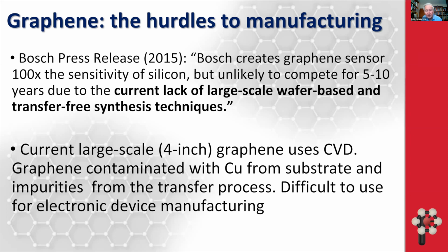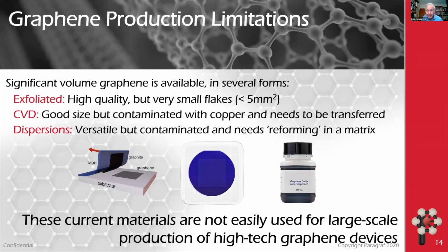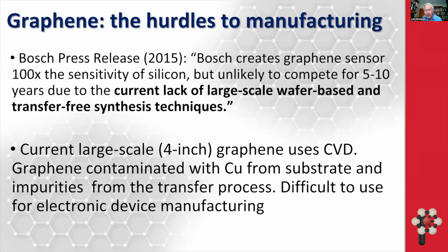So what existed in 2015 and what exists now is large area graphene, typically 4-inch, which is made using a technique called chemical vapor deposition, CVD. And in this technique, gases like methane are deposited on a heated copper substrate, and the copper's there because it acts as a catalyst to decompose the gases like methane. So you then get graphene on copper, and some of the copper atoms get into the graphene, so it's contaminated graphene. And then when you want to put the graphene onto a more useful substrate, you have to transfer it, and that puts more impurities in as well. So it's very difficult to use this method for making electronic devices because of contamination and the problem of transfer.